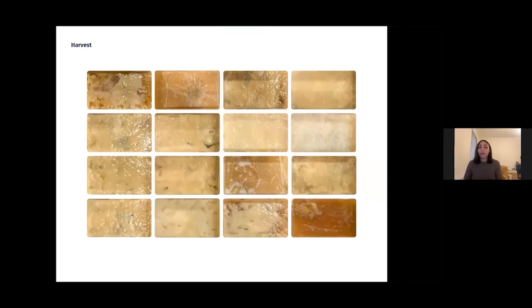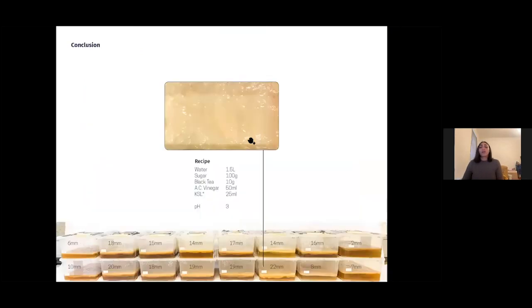As you can see, even though all of the ingredients were the same, the ratios did really affect the growth of the pellicle. So some of them were very, very thin, barely even growing anything, and some of them were thicker. So that led me to this conclusion, which was that this recipe in this situation under these circumstances grows a pellicle that is the thickest and healthiest. And that is also apparent in the surface structure, that there aren't many irregularities in the surface due to the growth of air bubbles. And this one had grown to 22 millimeters, which was a very good achievement at this point.